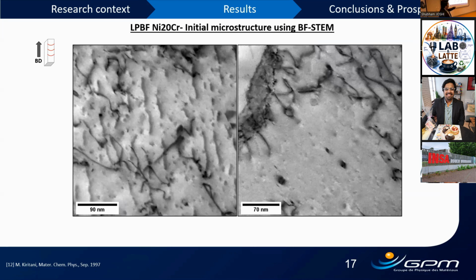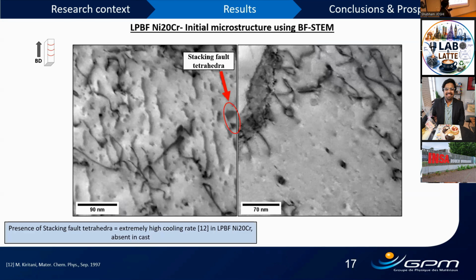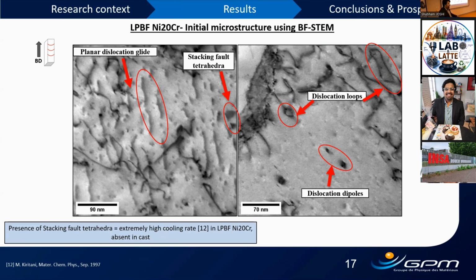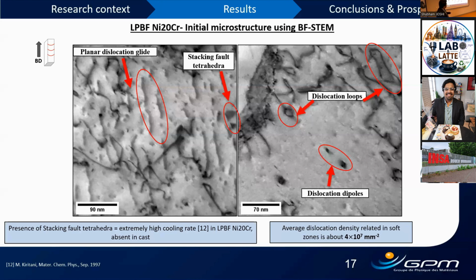Again, the building direction can be seen upwards, and it led us to see that we have stacking fault tetrahedra, dislocation loops, dislocation dipoles, and planar dislocation glide in terms of dislocation subfeatures. This image is just an example of an extensive analysis that we did, but using many images, we computed the average dislocation density in soft zones to be 4 × 10⁷ per millimeter square, and this will be used in the modeling in the following slides.